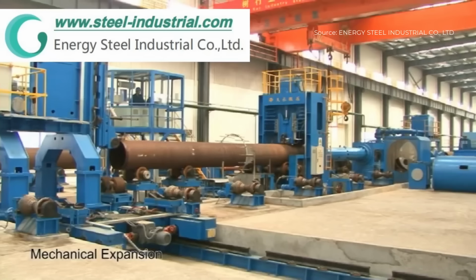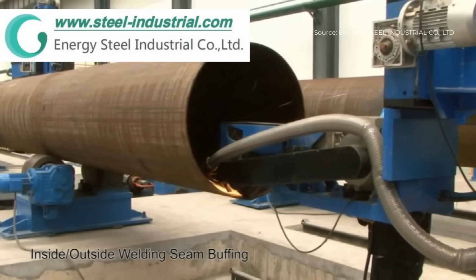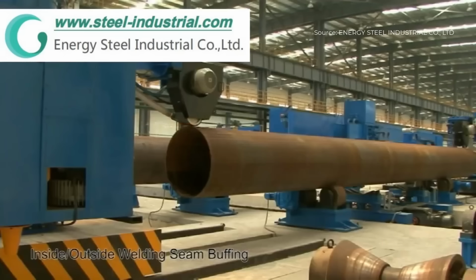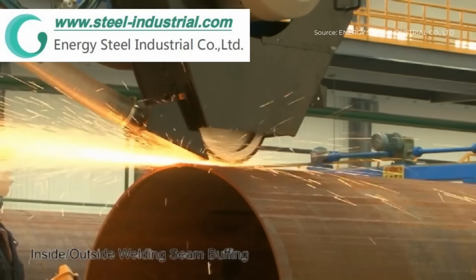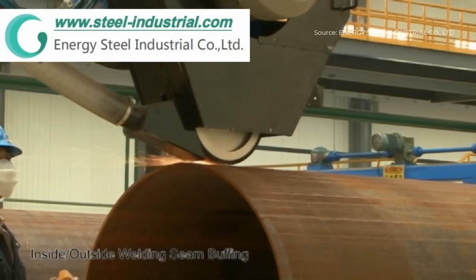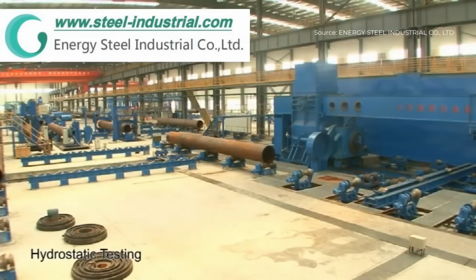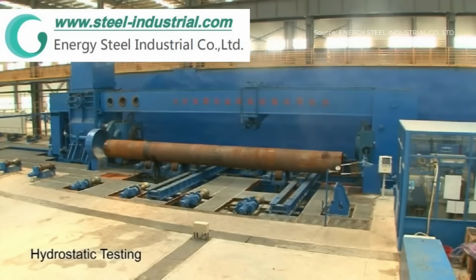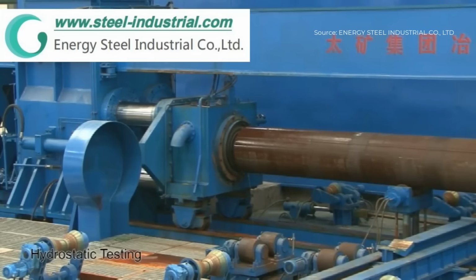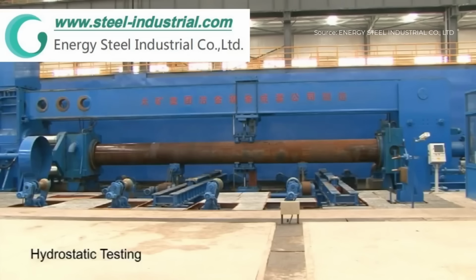Both pipe ends are cut to length by flame cutting, and the internal and external weld beads at the pipe ends are ground smooth. Hydrostatic testing is performed by sealing both ends and injecting high-pressure water into the pipe to verify its ability to withstand the specified pressure. Test results are automatically recorded and printed. After hydrostatic testing, phased array ultrasonic inspection and additional industrial X-ray inspection are conducted to re-examine the weld and heat-affected zones.